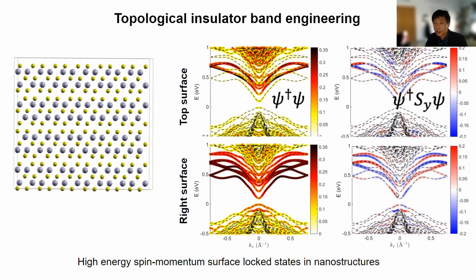And that spin momentum locking is sort of expected because of time reversal symmetry. This material is non-magnetic. So if you go from plus k to minus k, the up spin should go to down spin. That's just a simple consequence of time reversal symmetry.